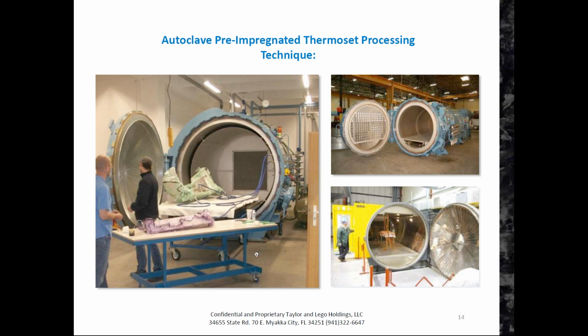So just to put it in contrast, the variation in thickness on, let's say, a fender for a Ferrari, and Ferrari is very good at doing this process. We know them, and they do an extraordinarily good job at it. A fender on a very high-end vehicle of theirs might have a variation in thickness of 20 or 30 thousandths of an inch from one end to the other. So, about anywhere from 0.5 millimeter to 3/4 millimeter approximately. That's still not accurate enough for some of our customers, so this approach is often not acceptable for us even. It's also a slow process. So you still have extremely slow cycle times with this.